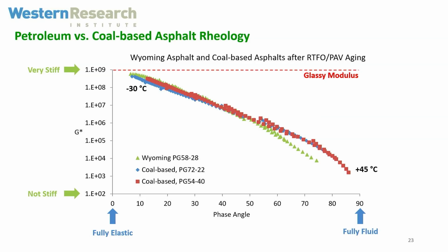So this tells us a lot of properties about the asphalt binder. The thing I want to point out is that the petroleum-based binder is very similar to the coal-based binders, and this is a kind of an unusual result. It's actually hard to do this with engineering asphalt binders.